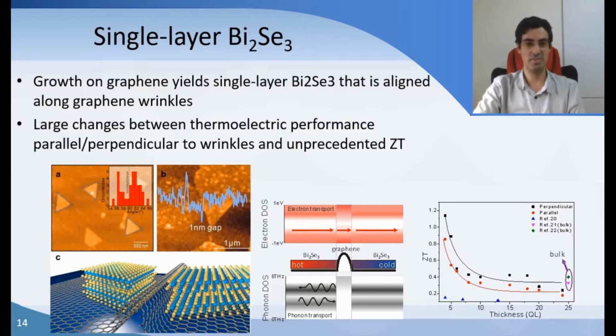And it also means that there is a wrinkle between adjacent flakes. In one direction, our wrinkles are only due to uniaxial strain, and uniaxial strain is induced by transfer, not by the relaxation during cooling. So this uniaxial ordering means that we're getting a material that has different electron transport and phonon transport across the wrinkles and along the wrinkles. So we have an anisotropic material where both phonons and electrons are affected.